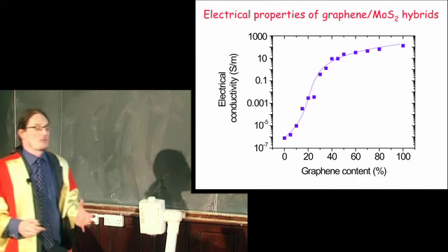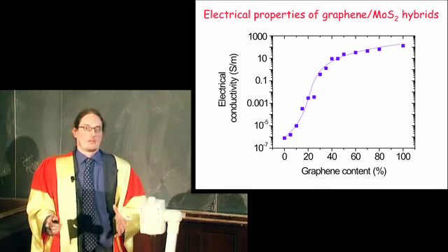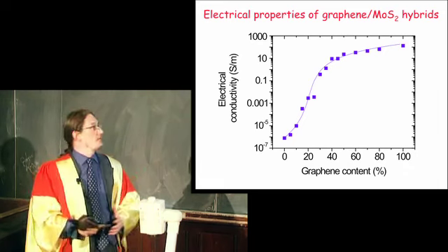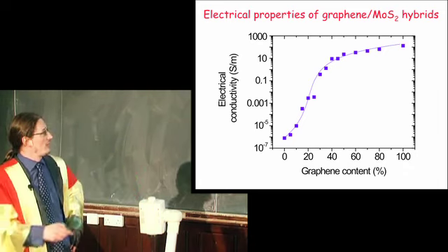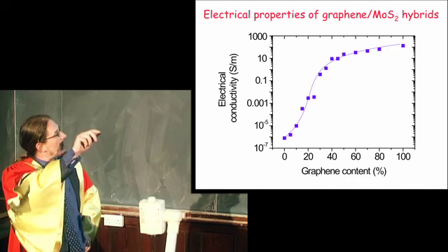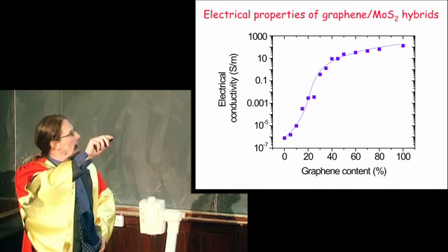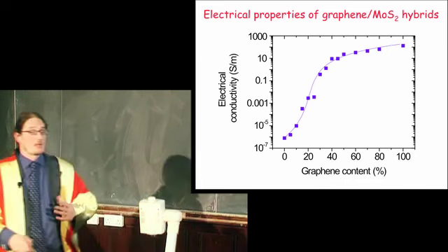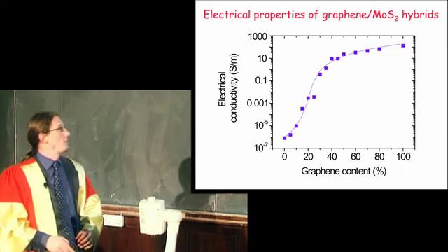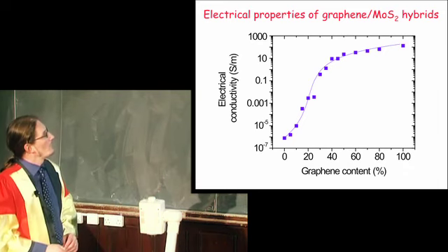And that sort of increase is more than enough to fulfill the requirements in areas such as supercapacitors, thermoelectrics, or other things. And nicely, again, as physicists, it's not just enough to show you can do it, you have to understand it. And this increase fits perfectly to percolation theory, both above and below the percolation threshold.